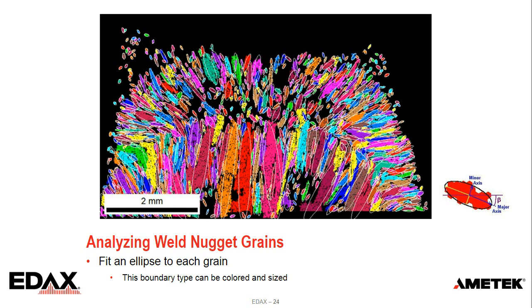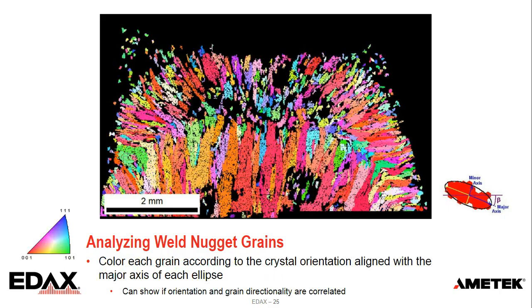So when we're looking at grains, we can get an idea of their shape and shape distribution. But from this, what I'm now doing is, we can see where the major axes are, and I'm showing what crystal orientation is aligned with the major axis. We can see that most of these, or at least a good number of these, are trending towards the red direction. That gives us an idea if some of that grows preferentially as the grains grow in that direction.